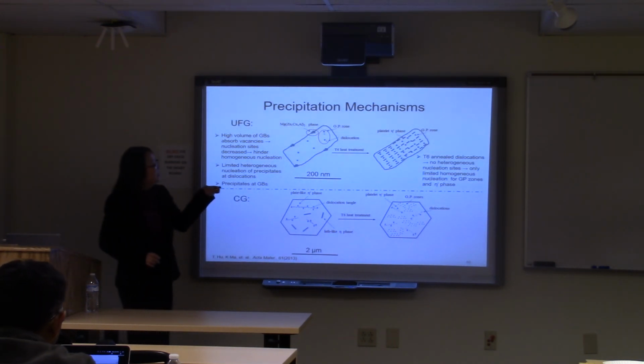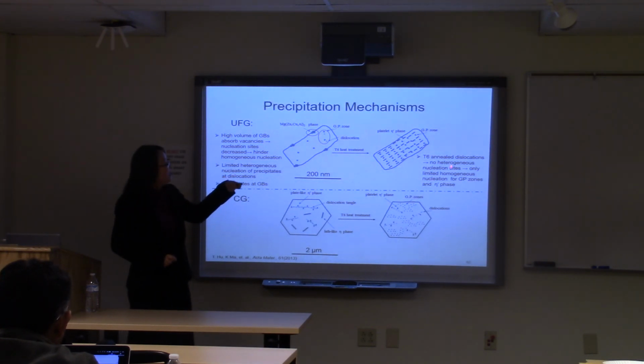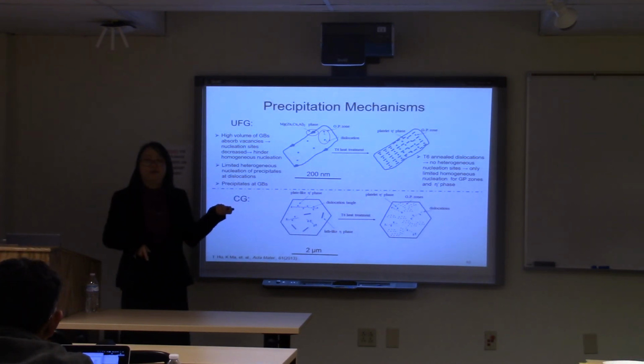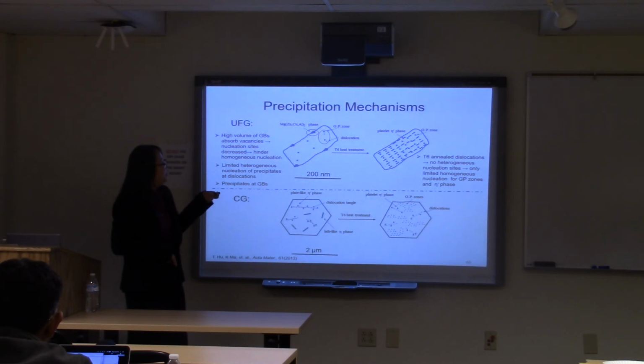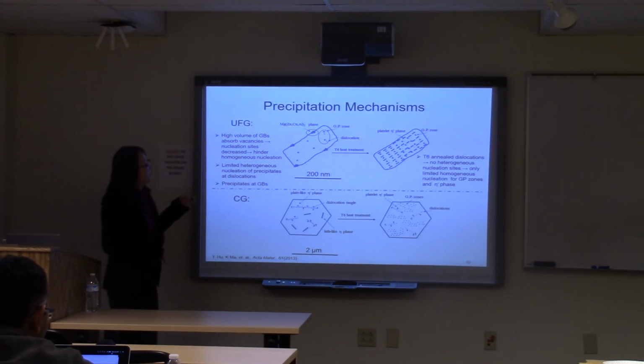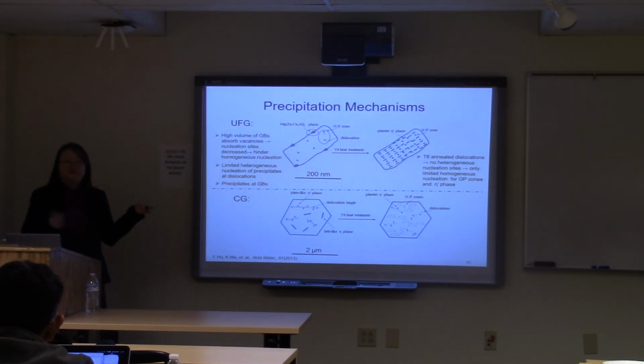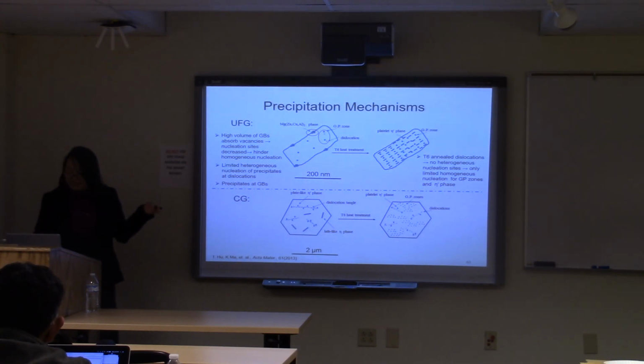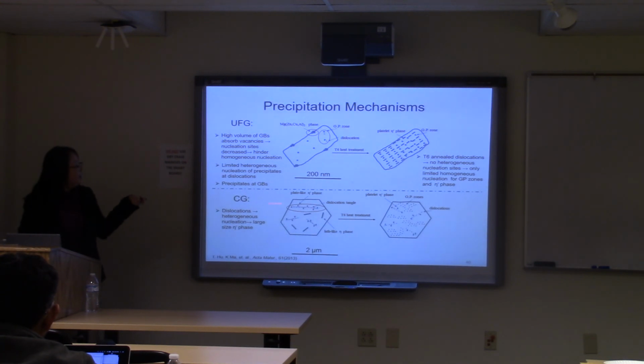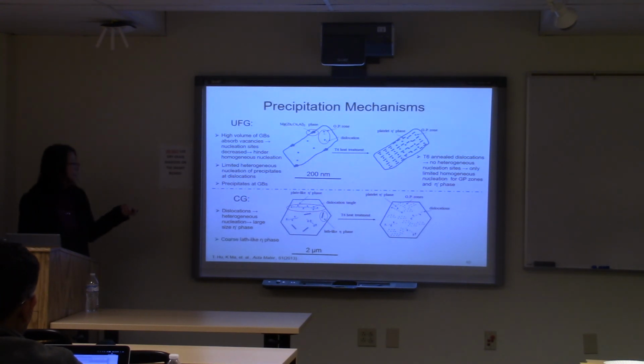And then after T6, although we still see precipitates, the thermal exposure now anneals the dislocations more easily because of those high volumes of grain boundaries. Compared to the traditional material, we get not much heterogeneous nucleation sites for the precipitates. And that's why we see from TEM only a very limited number density of the precipitates. And this is just a comparison in the coarse grain. We can see a lot of dislocations in the microstructure, which assist the heterogeneous nucleation for large-size eta prime phase. And we even see much coarser lace-like eta phase.